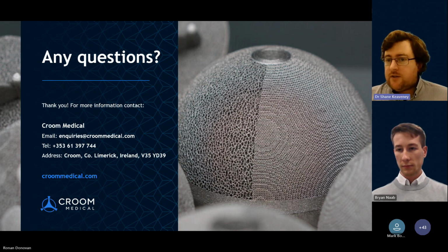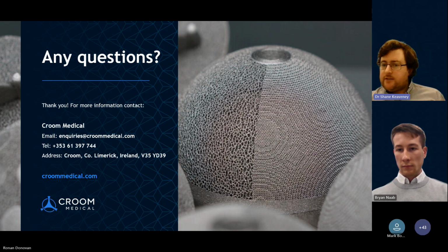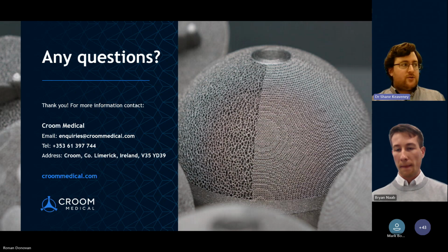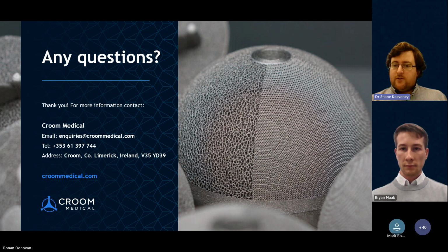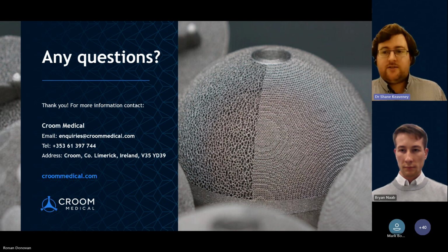Okay, and I do see another one there from Franz Mohlmann. It seems more of a question than a comment, but it's a good one. They've seen some differences between software in terms of stress concentrators related to filleting. So I think that's a very important point. It's something we would do when we're doing our design for additive manufacturing: look at the component, the potential for, as Bryan has mentioned, surface roughness that might influence fatigue, any sharp corners, any square edges, this type of thing. Obviously, they will act as concentrators, and if we're adding on porous structures, that interface too. So we'll pay quite a lot of attention to that, but it's something we'd work on during the design for additive manufacturing stage.